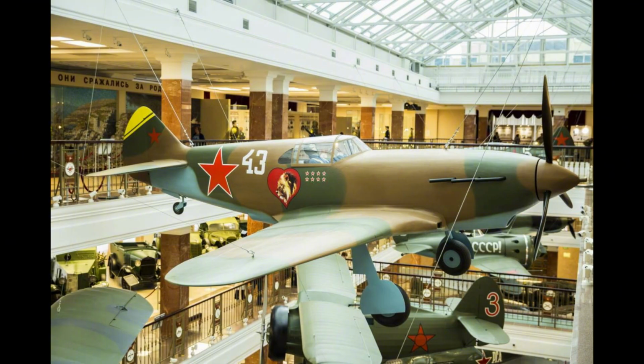Wooden propellers develop stress cracks requiring frequent inspection and replacement. The phenol formaldehyde resin outgasses formaldehyde vapor in hot weather, creating respiratory irritation for ground crew working inside fuselages. Winter operations prove particularly difficult. At temperatures below -20 degrees Celsius, the delta wood becomes extremely brittle. Several aircraft suffer wing failures during high-speed flight in cold weather.